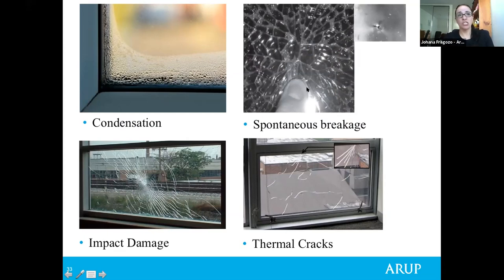Spontaneous breakage occurs in toughened glass. When glass is heated in the toughening process, nickel sulfide inclusions, which you can see on the right-hand side of this photo, shift from a low temperature state to a high temperature state, and they shrink. As the glass ages, these inclusions return to their low temperature state and expand, and that creates this spontaneous breakage. It usually takes around 5 to 10 years to occur. And of course, impact damage, which is quite common and due to external forces. It could be from a BMU, from maintenance activities, or from vandalism.